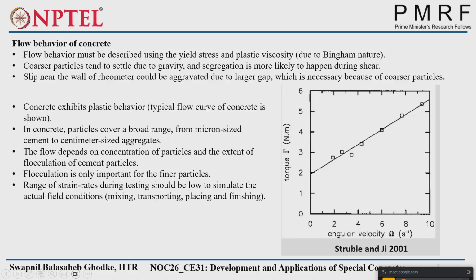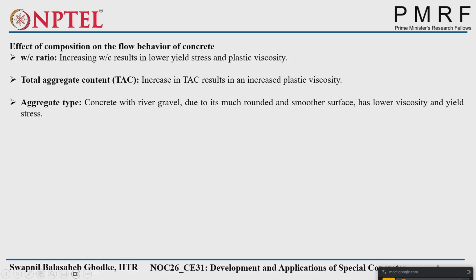The range of strain rates during testing should be low to simulate the actual field conditions: mixing, transporting, placing, and finishing. Very important sentence. Apart from that, why do we have to go for the low strain rate? Because at a high strain rate, there is a chance for the coarser particles to settle down. So that's why we have to go for the low strain rate, and it will also simulate the actual field conditions of mixing, transporting, placing, and finishing.